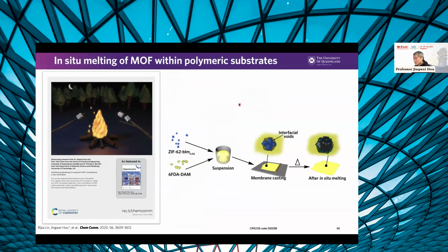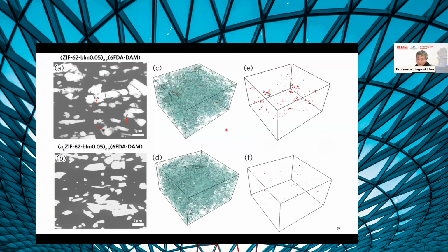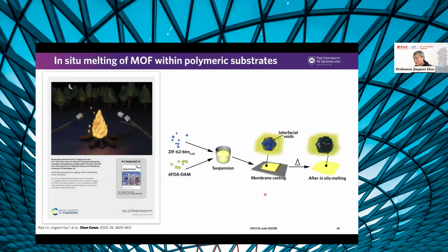Initially, I talk about composite membranes. Once we have defects in the composite material, they may stay there forever for traditional materials. But in our case, we can melt the MOF glass inside the polymer and make the membrane, I wouldn't say defect-free, but with the voids reduced by a significant amount. The top one is the composite membrane before melting. You see all the red bits represent the voids at the interface. But after melting, it becomes much, much less. We have done the quantitative analysis, and it reduced by 98%. That actually delivers a much more selective membrane. So we were really excited to call this process toasting MOF-mallows. It's like toasting marshmallows when you are camping.